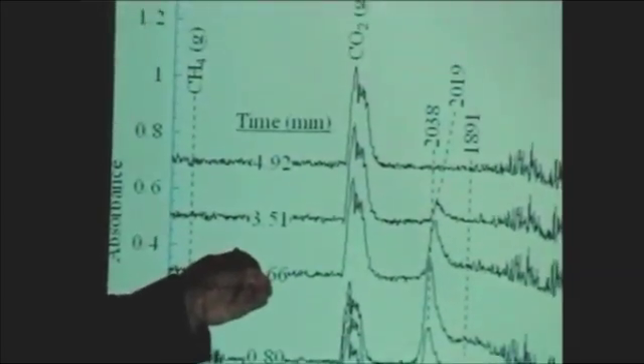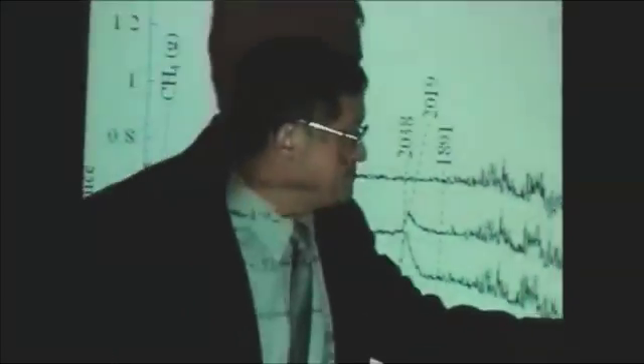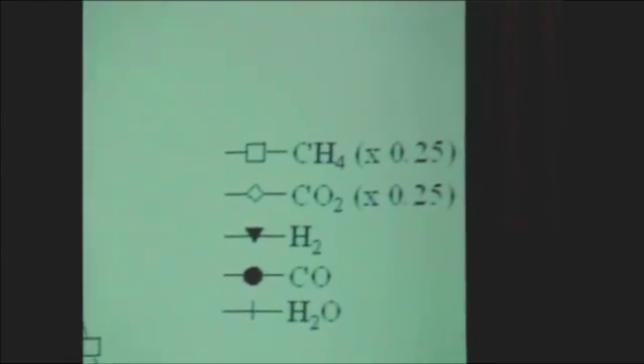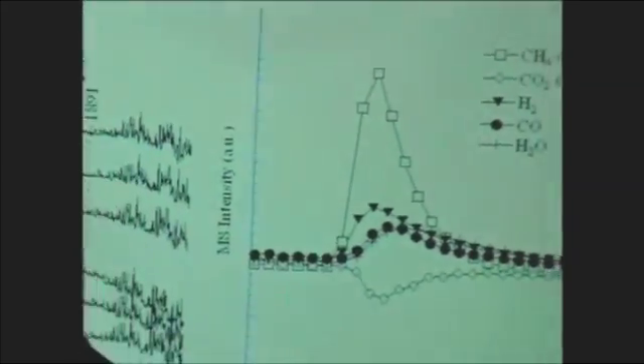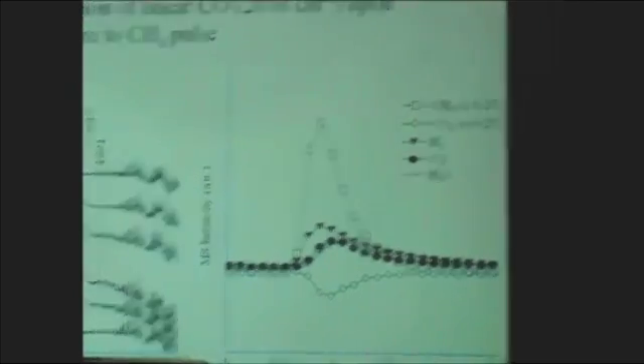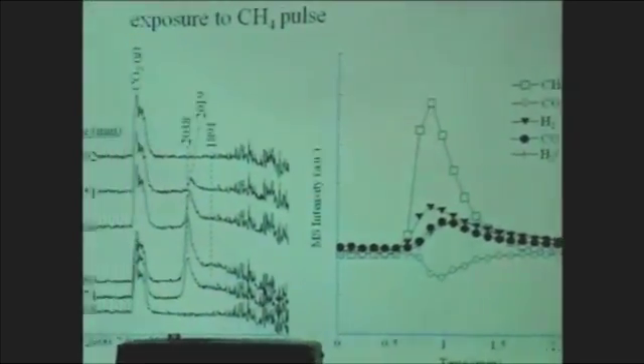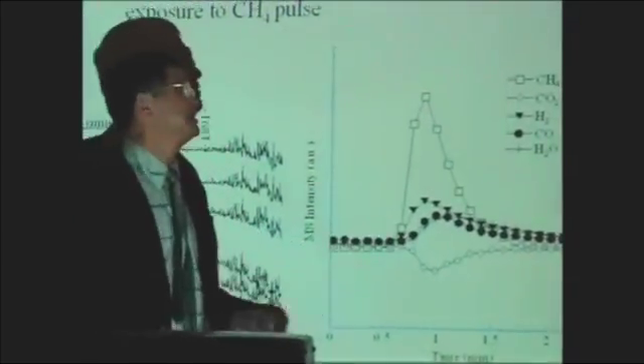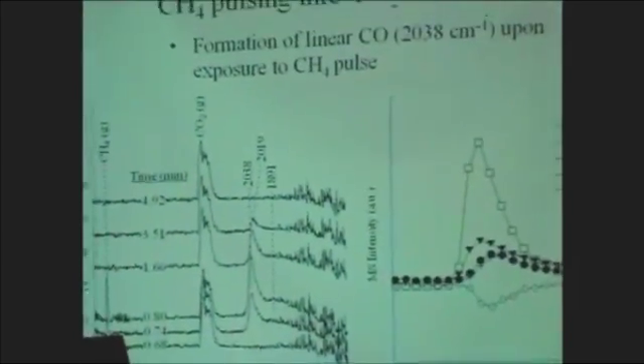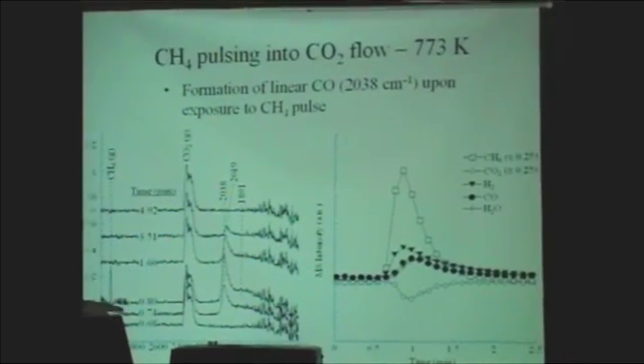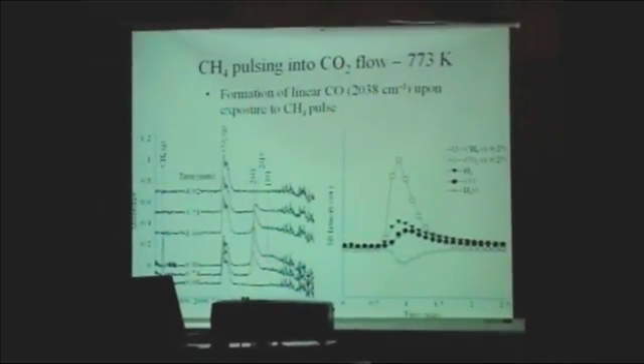And as this pulse of methane enters the reactor, we also see the product formation by the mass spectrometer. As you can see here, the methane comes in, and the first species produced from this reforming reaction is, in fact, hydrogen. Hydrogen comes out first, and then CO comes out. So from this result, we can see the formation of hydrogen is quite an easy step in this reaction. Formation of hydrogen always leads the CO formation. CO formation is slower than the hydrogen formation.